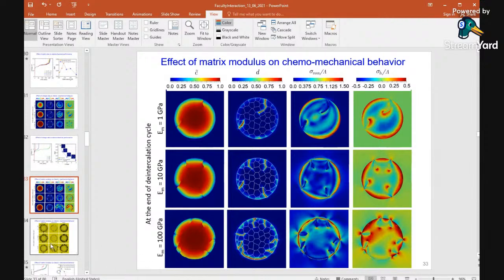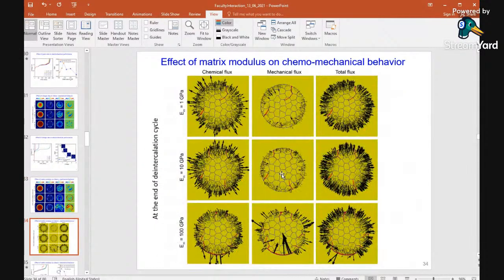Let me show in much more detail what is happening with the deintercalation process. The same thing, we are trying to understand this flux. What we see is that the chemical flux is going outside, which is fine. But in case of 100 GPa or a very hard electrolyte, mainly the solid electrolyte, you see the interface between the particle and matrix fractures. So essentially it is cutting the path, and it will not allow anything to go outside on that path. So we see the intercalation process is significantly hampered at those particular grains.